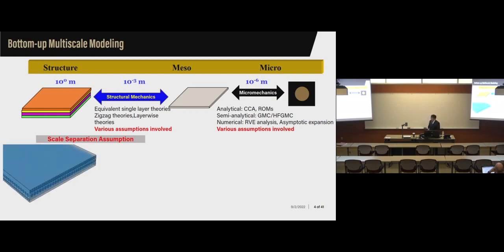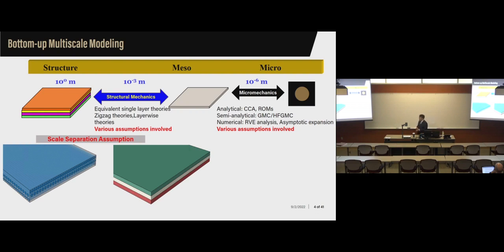For example, take the unidirectional fiber-reinforced composite. When we do this two-step micromechanics and structure mechanics, you basically replace the original heterogeneous panel with a panel made of 3 homogeneous layers. And it's okay if your fiber is indeed much smaller than the layer thickness. Traditional fiber-reinforced composite is the case for them. It would be okay for the global behavior, like displacements, vibration, and buckling for the system, but not okay for the stress, for one simple reason: we create artificial discontinuity between the layers. If you have perfect bonding, actually, you should have resin material there, the real material discontinuity between the fiber and matrix, not between the layers.